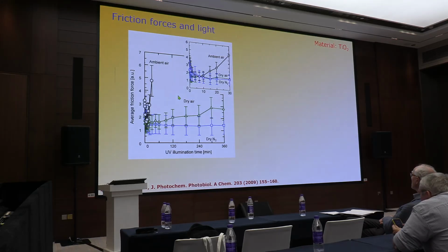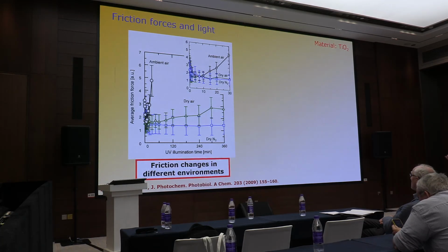Well, researchers published that there is an effect on friction forces due to light. It's not easy to see the effect, but there is an effect. Here, for example, this is dry nitrogen and dry air, and this is the average friction force. The material is titanium dioxide, which is photoactive. This is very important because to see the effect, you need a photoactive material. You need a material that absorbs light.